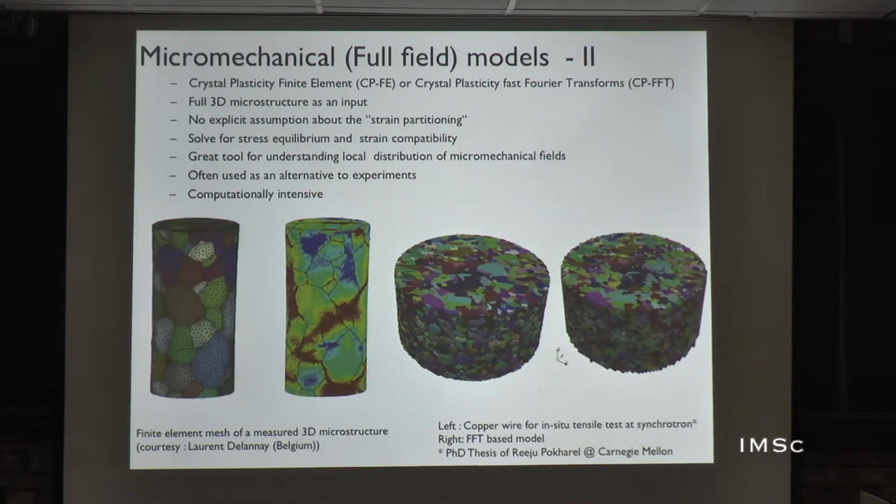One example I can think of is people who are trying to understand delamination at the grains. One easy way to do that is they take continuum elements and insert what is called a cohesive zone element, and it comes with its own constitutive property. You say for a certain traction opening, you open up that particular boundary. That depends a priori on deciding what the model for the interface region should be, and that allows you to then take it forward.